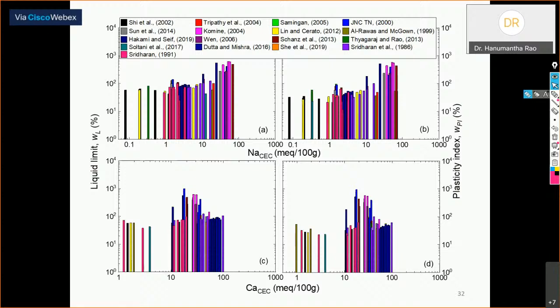Now again, when I talk about NaCEC or CaCEC, when I say these two terms, this is not an internal component of that particular soil. This sodium is externally induced in the pore solution, which is adhered to the clay particle. Suppose you introduce the sodium alone into the expansive soil, then we can see one kind of swelling behavior. Or if you introduce calcium as a pore solution, then we can see another variety of swelling. Here it is related with the liquid limit.